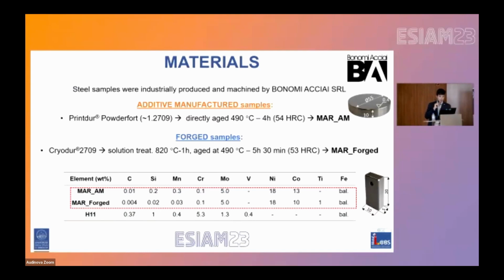As regards the forged samples, they were cut out from a forged round bar, and for both the materials, the samples were tested after aging treatment, with the treatment parameters chosen in order to obtain a similar hardness value. Furthermore, H11 die casting steel samples were also machined and compared.